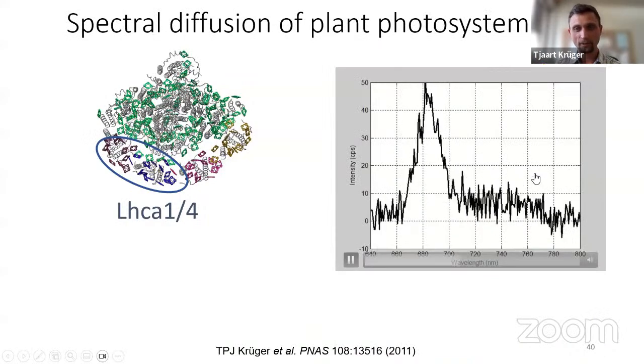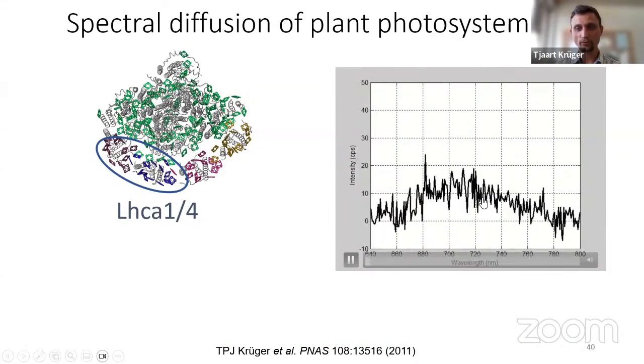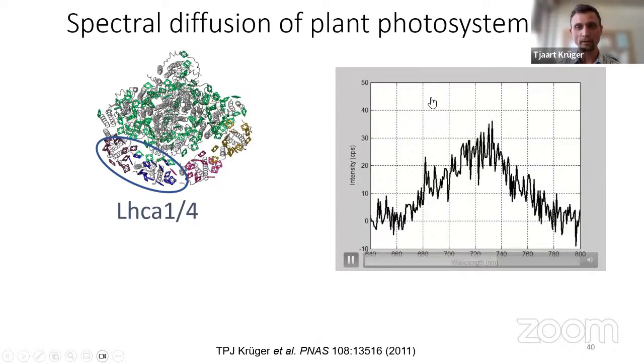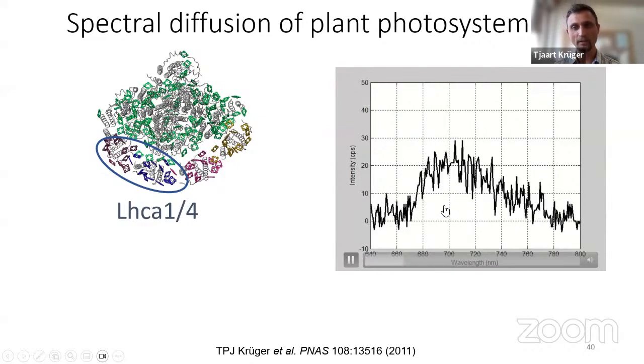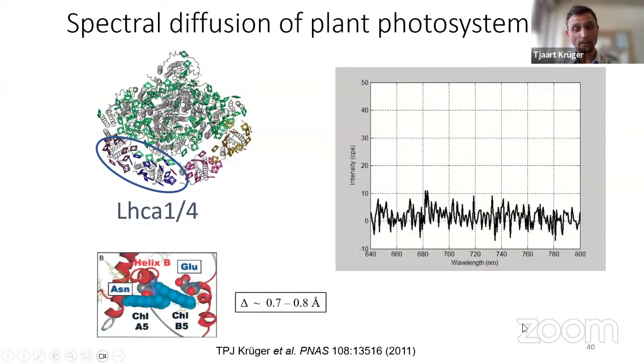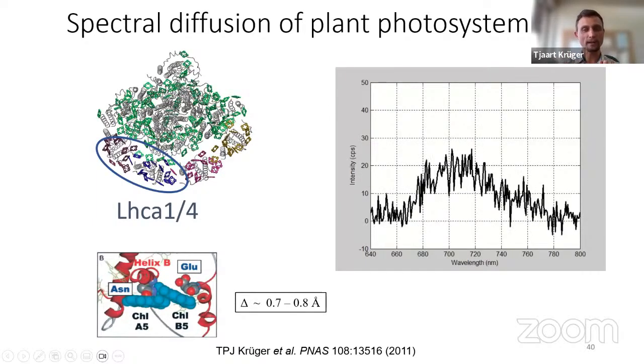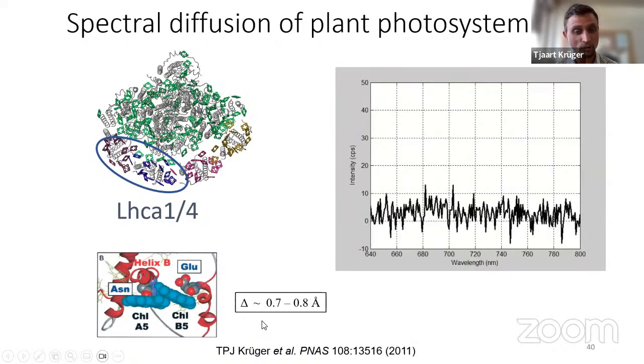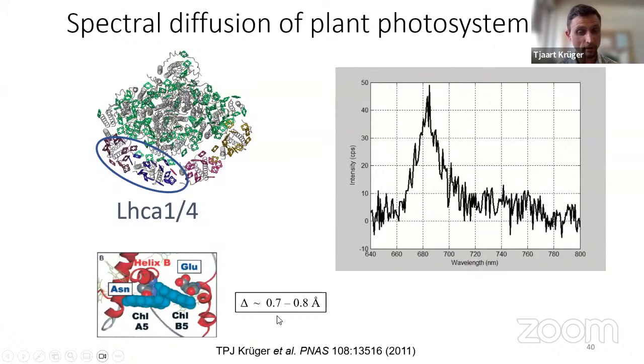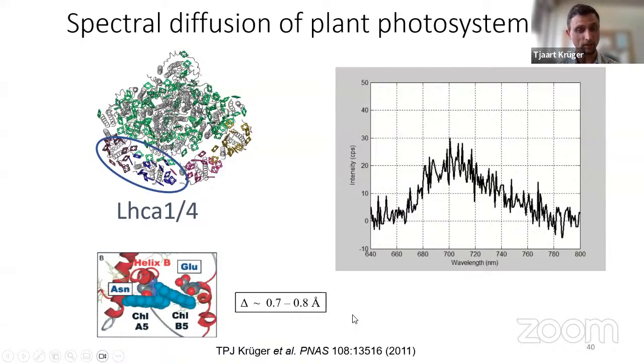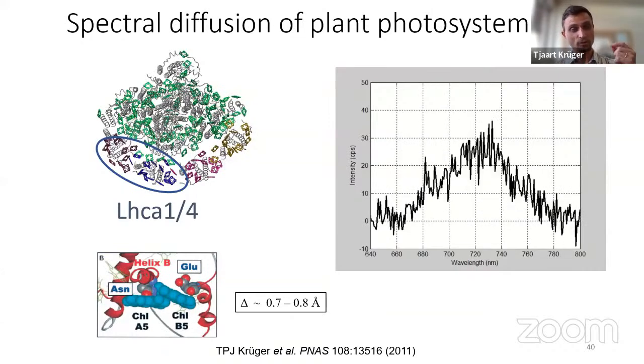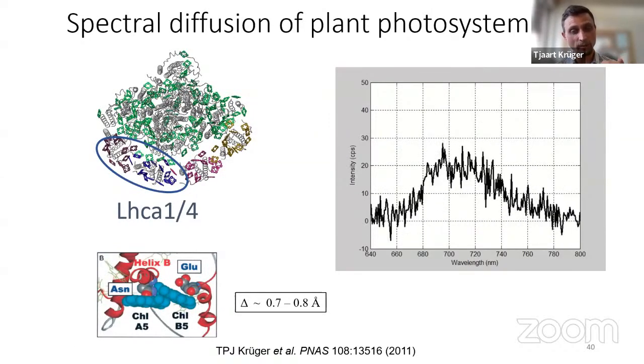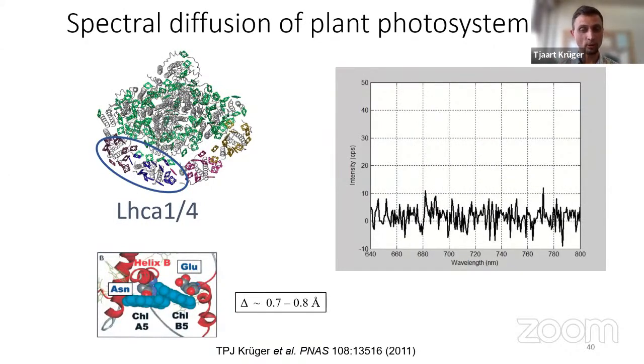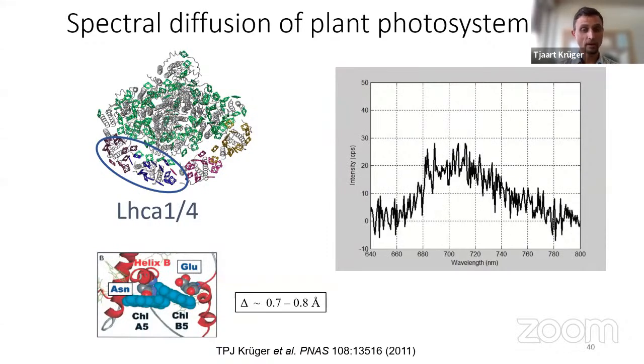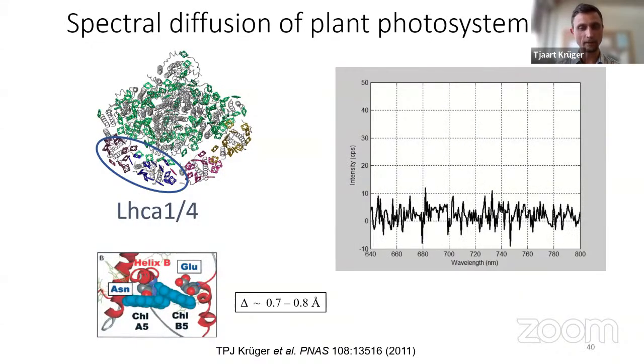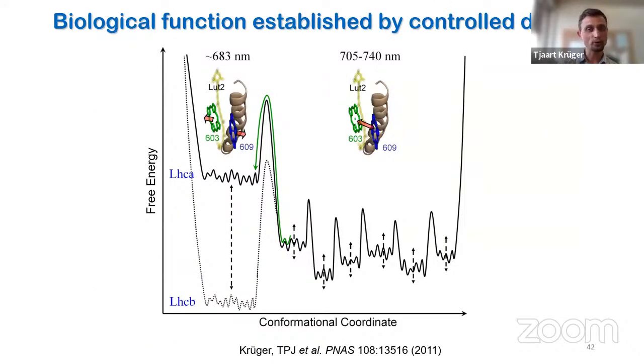Okay, so here's what one can see. So the red state is switched off, and then only the blue emission is still present, and this is a completely reversible process. Okay, so this switching off and on of the red state happens due to a change in the distance between these two chlorophyll rings of 0.7 to 0.8 angstrom. Okay, which means that this charge transfer exciton mixed state is extremely sensitive to distances and to the local environment. Just a very small change in the environment can switch this red state off completely. Okay, so photosystem 1 can behave like photosystem 2 and the other way around.